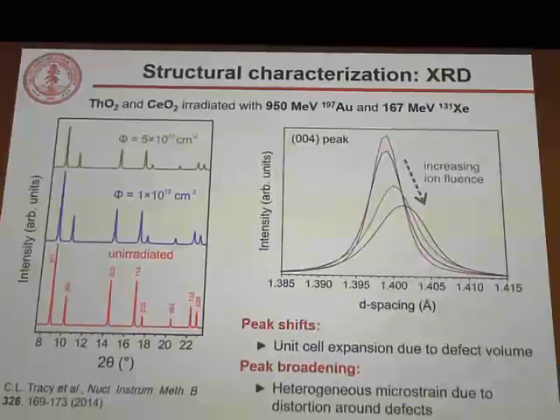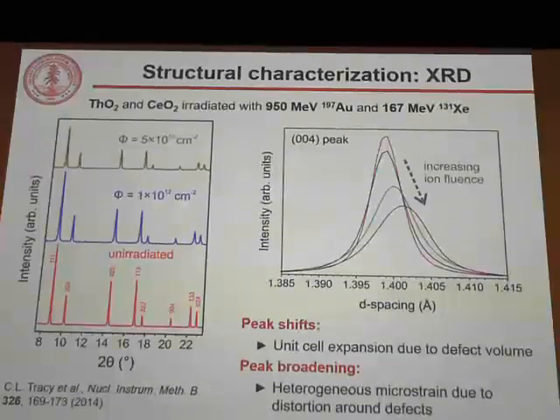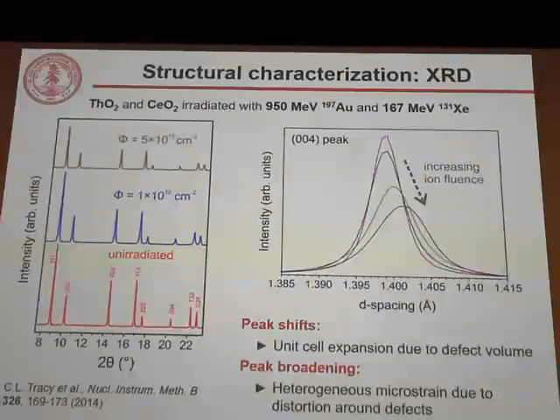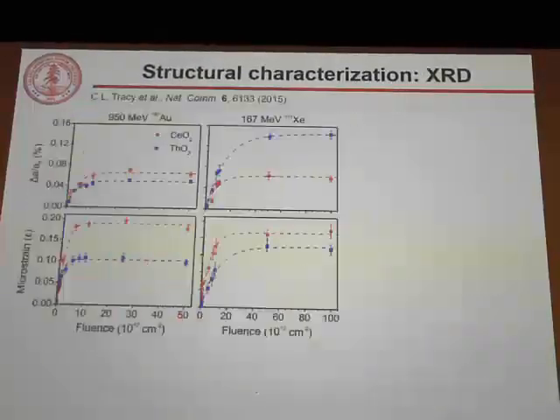First is a shift of the peaks to higher D spacings, which is indicative of expansion of the unit cells, expansion of the structure, due to defect accumulation. Second, we see broadening of the peaks, which indicates heterogeneous microstrain, again, structural distortion, due to defects forming. We can quantify these two changes.